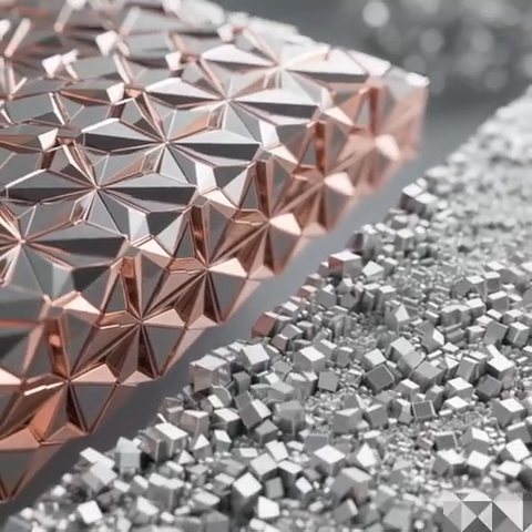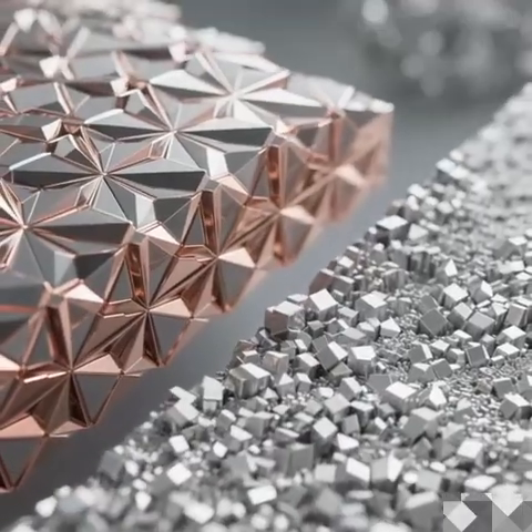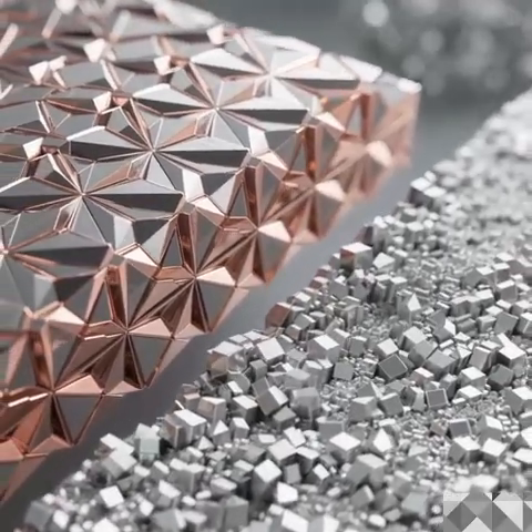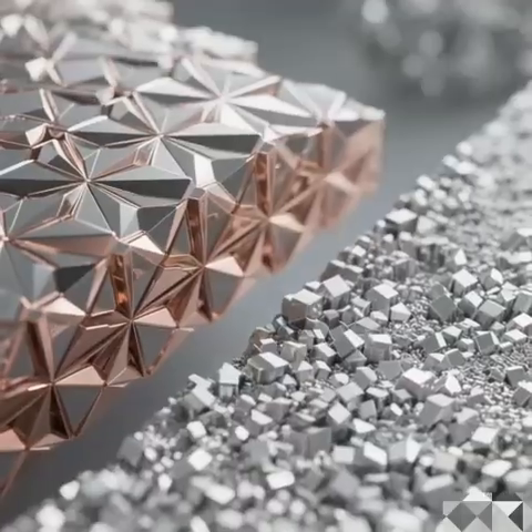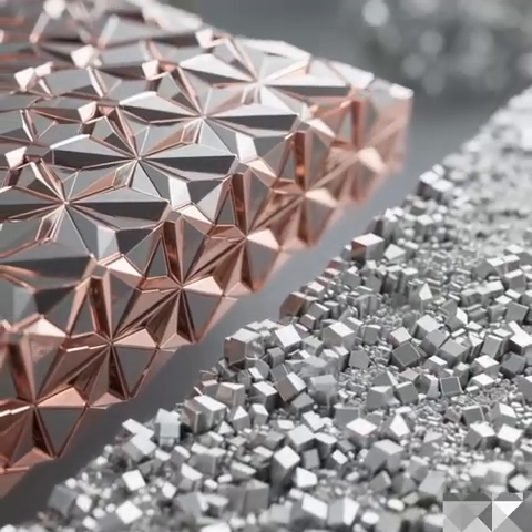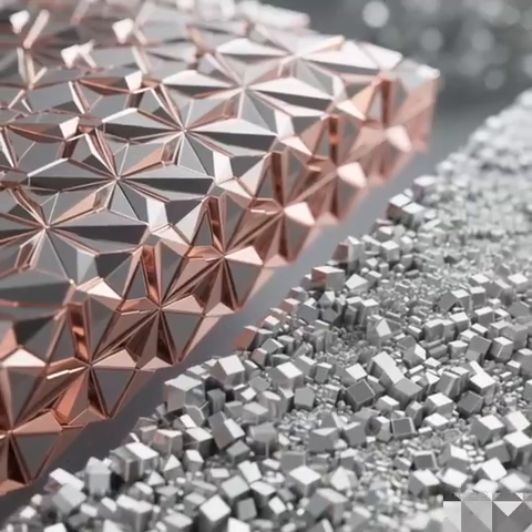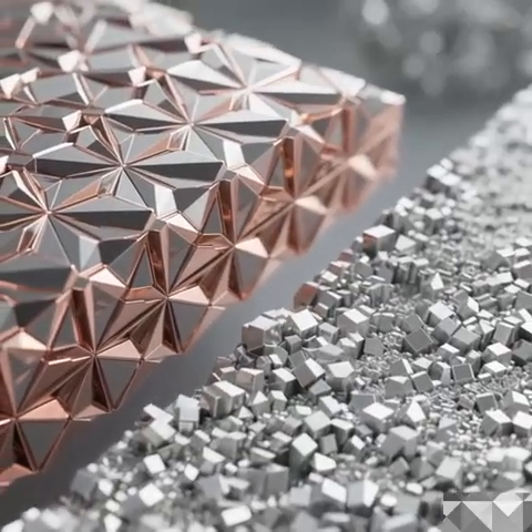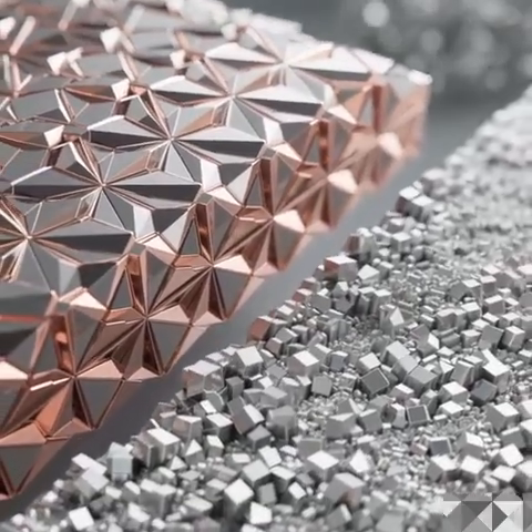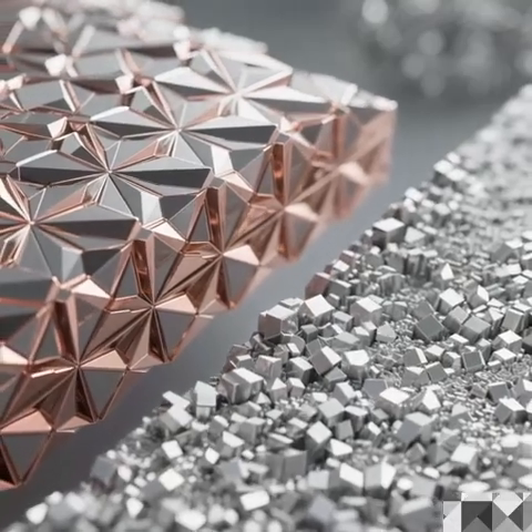there's a much thicker layer, maybe 3 micrometers, of coarse-grained copper, CGC. Coarse-grained, so bigger grains. Much bigger grains. And this dual-layer setup is really quite pragmatic for manufacturing. It tackles the impurity problem head-on. How does it do that? What do the two layers do?